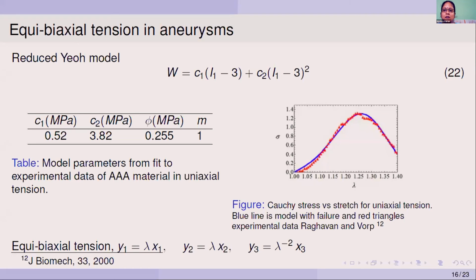And this figure shows the Cauchy stress versus stretch for the model and experimental data. This blue line is for the model, and these red triangles represent the experimental data. And this equation is for equibiaxial tension for an incompressible material. So by following the same procedure as for the case of rubber bearings, we arrive at